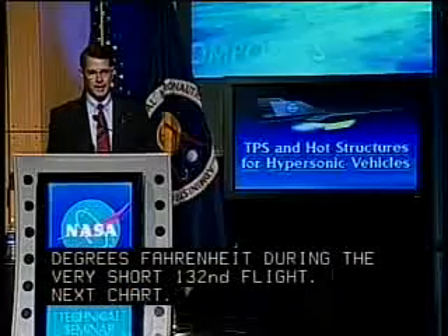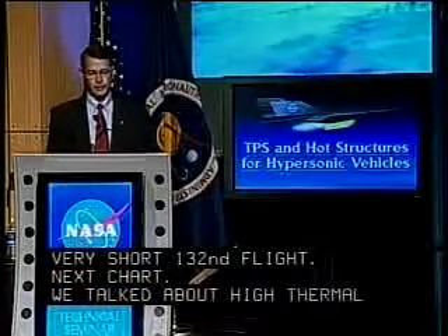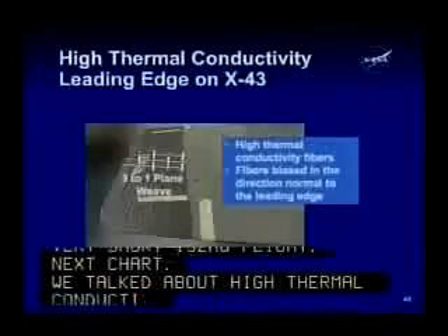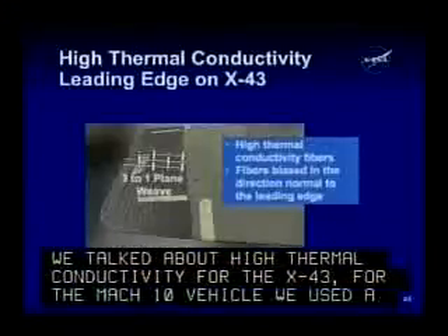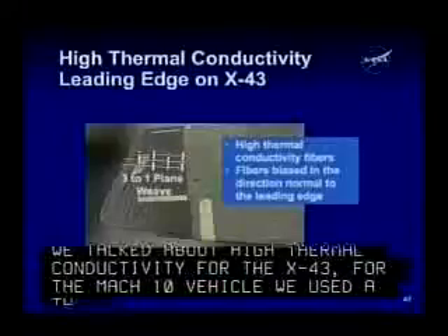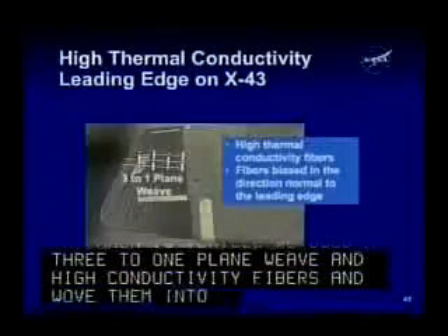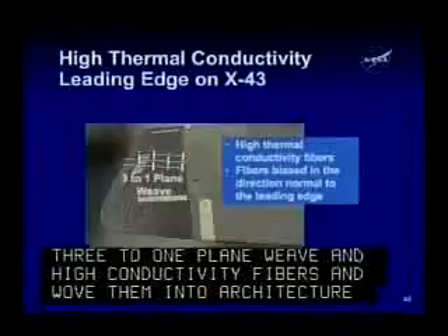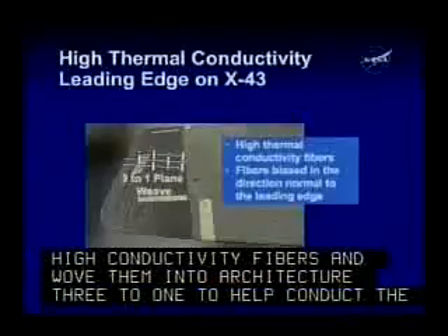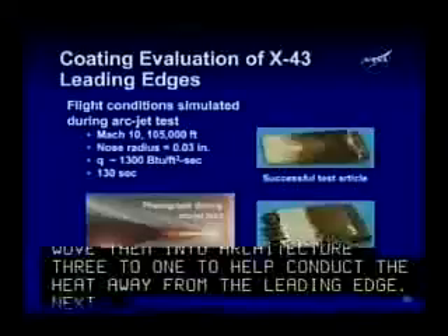We talked earlier about high thermal conductivity. For the X43, for the Mach 10 vehicle, we used a 3-to-1 plane weave. We used very high conductivity fibers and wove them in a 3-to-1 architecture to help conduct the heat away from the leading edge. Next chart, please.